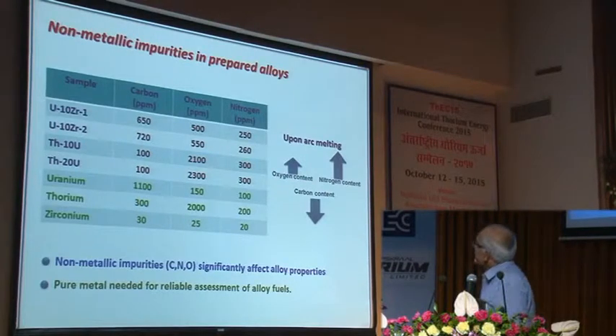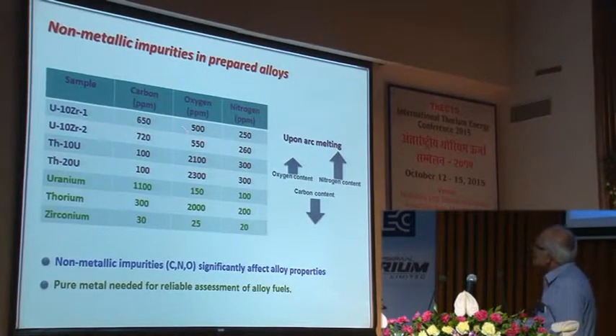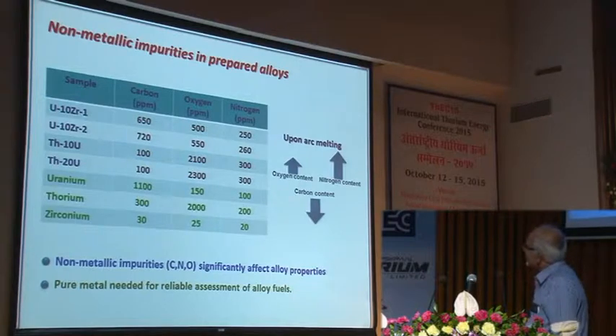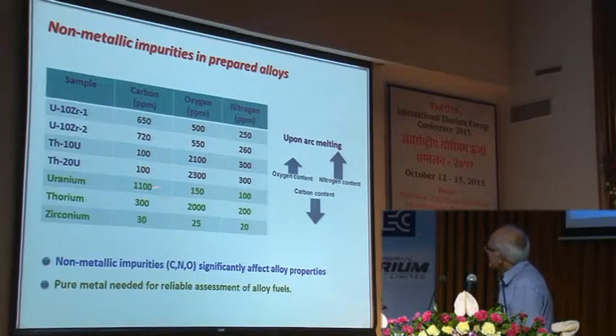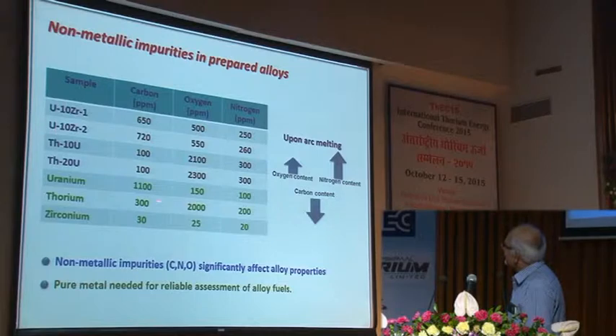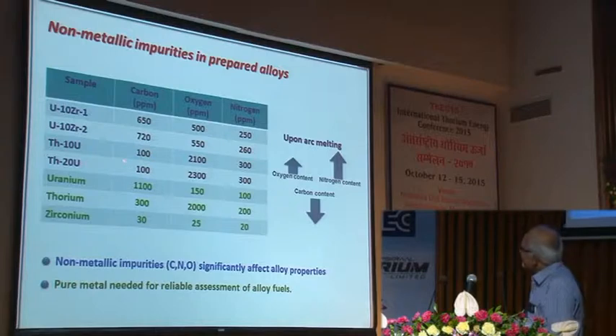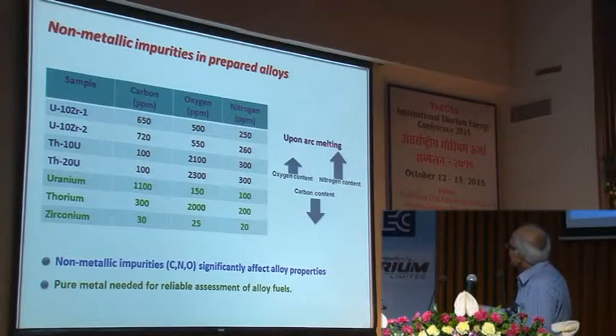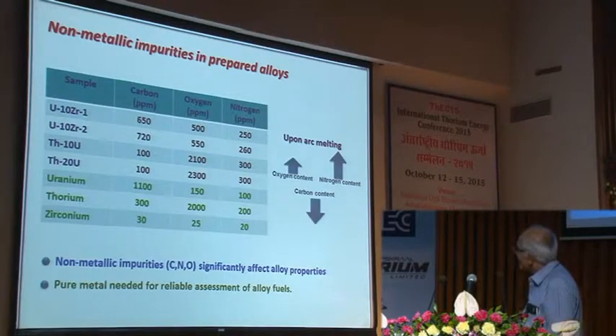Now, in the prepared alloys, there is the concern of the non-metallic impurities, and here you can see that to start with the uranium and thorium, the carbon, oxygen, and nitrogen are 1100, 150, 100 and 300, 2000 ppm. But when you form the alloy, you find that after arc melting, the oxygen content increases, the nitrogen content also increases, and the carbon content goes down.